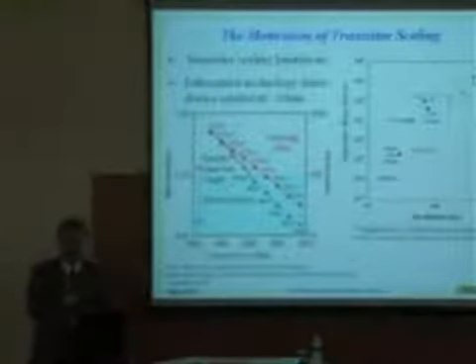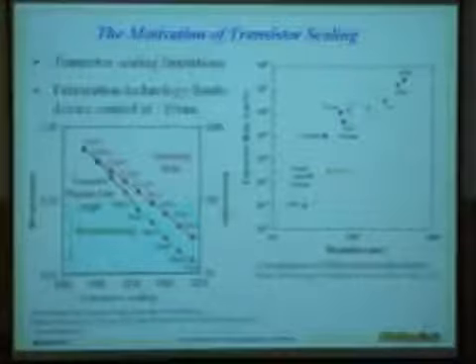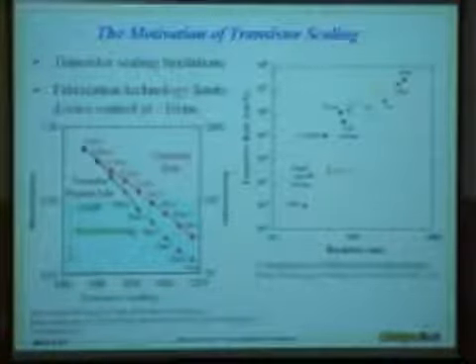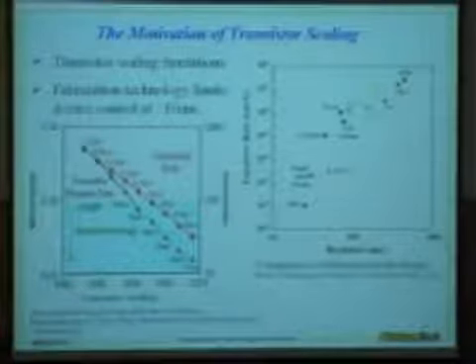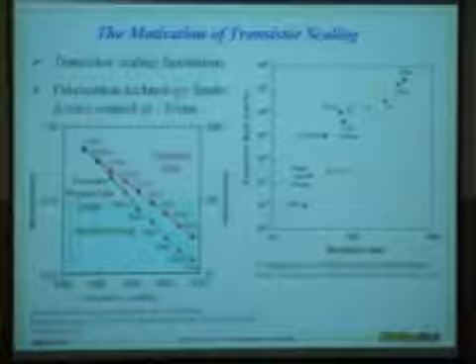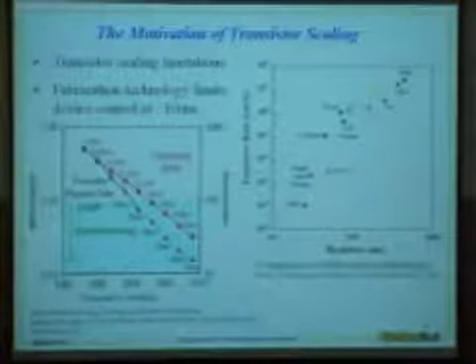So one of the key technologies that limits this is the ability to produce features at these dimensions, and that has been one of the main pressures on the semiconductor industry and on the industry that supplies equipment to it, in producing tool sets that can produce features below 40 nanometers, which is basically right in the middle of this graph here. X-ray was a favorite for a long time in the 80s and early 90s as a migration path to smaller features. In reality, the cost, expense and difficulty of producing X-ray based lithography has pushed that trend to the side as laser based light sources have come on at much shorter wavelengths and have kept the industry pushing into these extreme ultraviolet ranges.